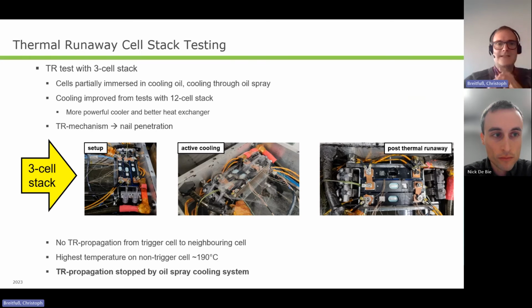Then we come to my last slide, thermal runaway testing of the cell stack. We did till now two different test configurations. This was the second one. The first one we had to improve in terms of cooling. We didn't have enough cooling power in the first test, so it was not a realistic situation compared to the battery pack itself. But the second test had improved immersive cooling and spray cooling. You can see it here. Here is oil on the bottom of the box, and those are the sprays which cool the batteries.